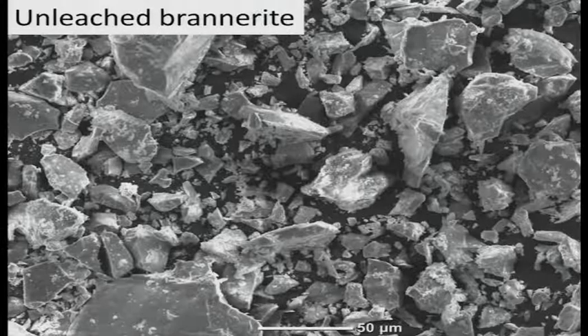Electron microscope images, which I'll be going through shortly, show the formation of a secondary phase, and the spot EDX analyses show that the secondary titanium is forming as a separate phase. It's not forming on the surface of the brannerite, which is something we thought might happen initially. So the initial unleached material is fairly jagged and angular under the electron microscope, with flat faces and sharp corners.